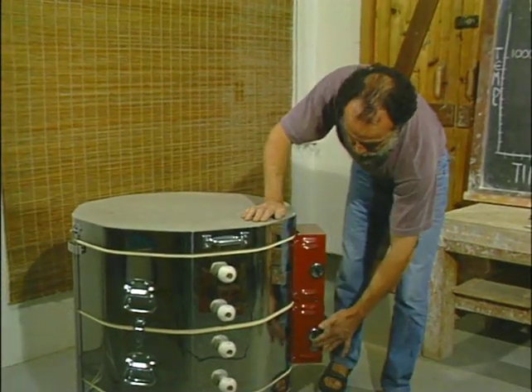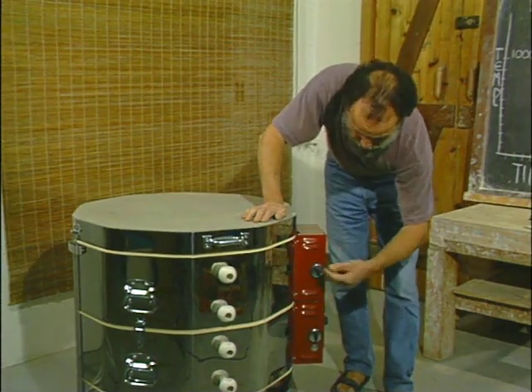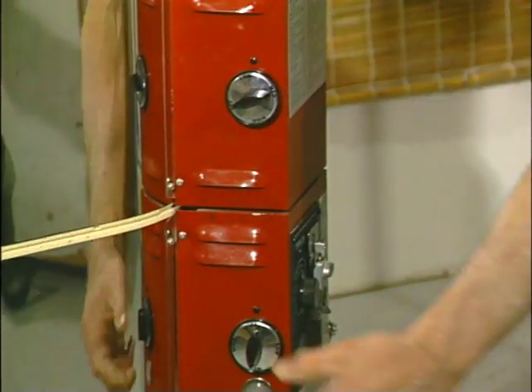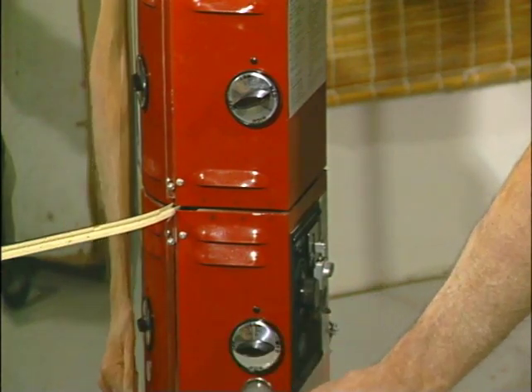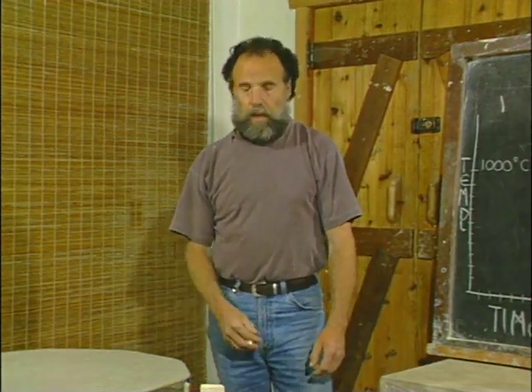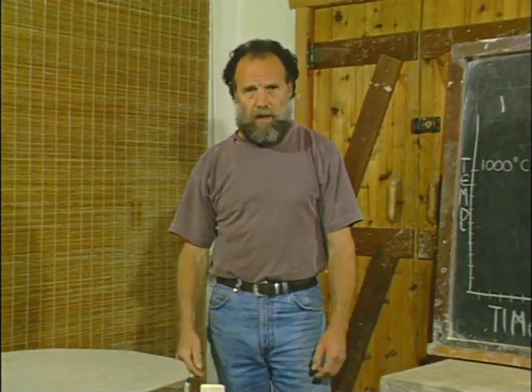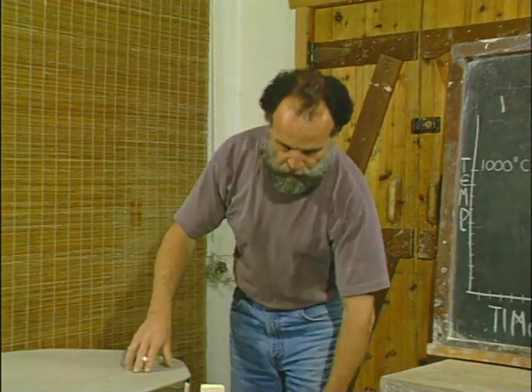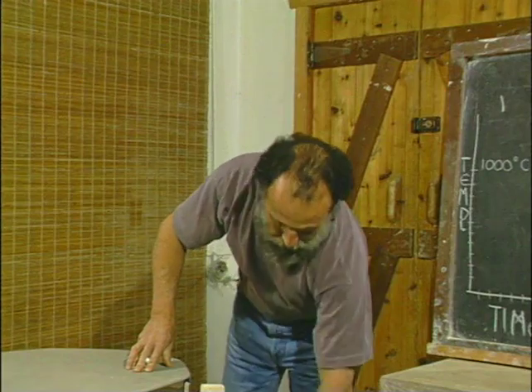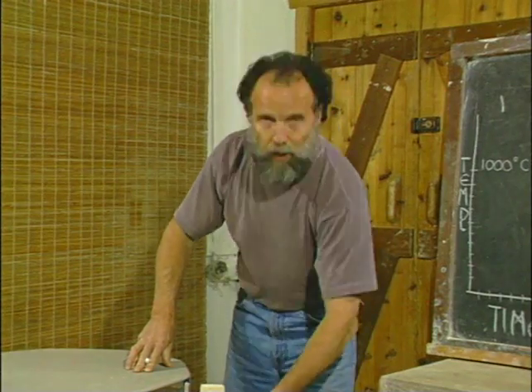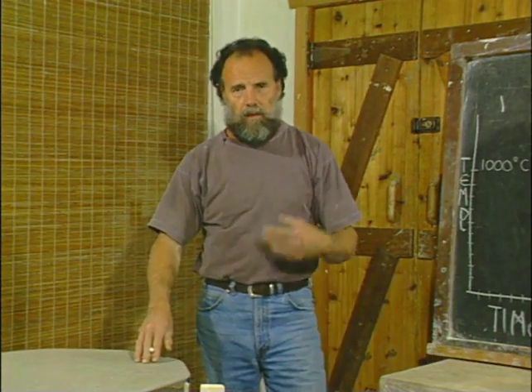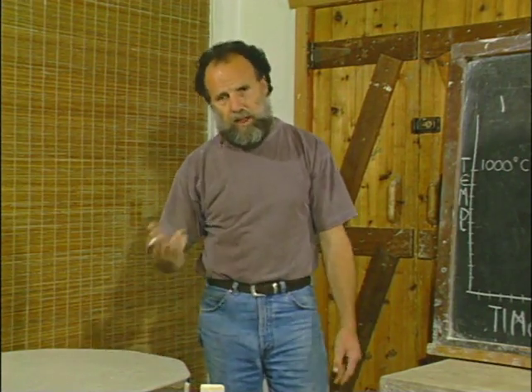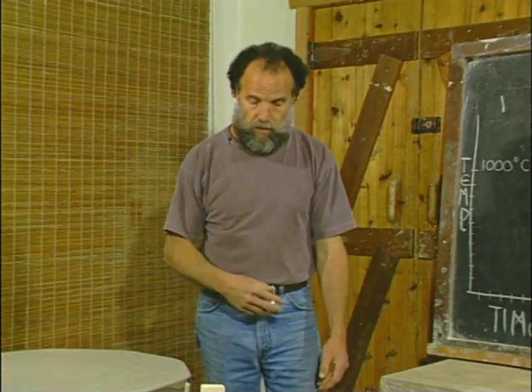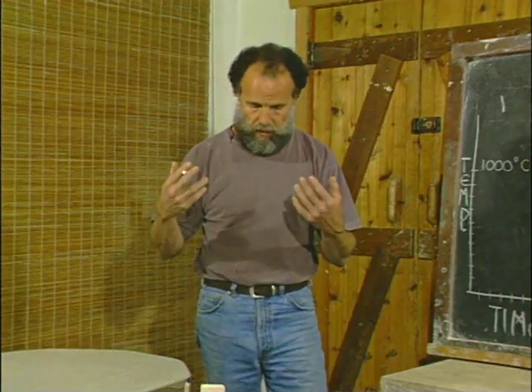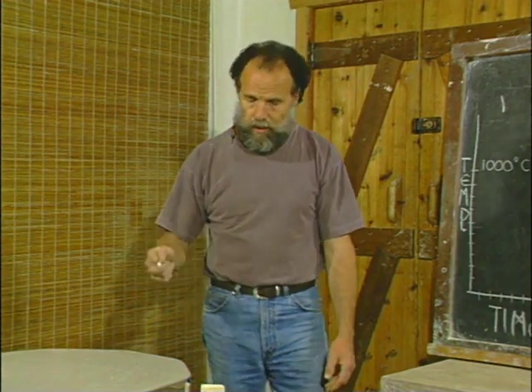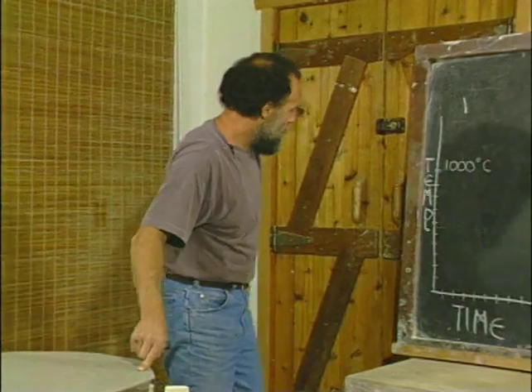Okay, these are the control switches. This is a manual kiln, remember, so that you're in charge of this. So what we'll do first of all is turn the two switches on to low. The kiln's now going, and we'll leave it go on the low setting now for a couple of hours. And in a couple of hours we'll turn perhaps the bottom burner up to medium, wait an hour or so, turn the top one up to medium, and let the firing progress. The idea here is that you've got to advance the temperature slowly, and there are several points in the firing where it's important that the rate of progress be quite slow. Perhaps I could illustrate that on a graph for you.